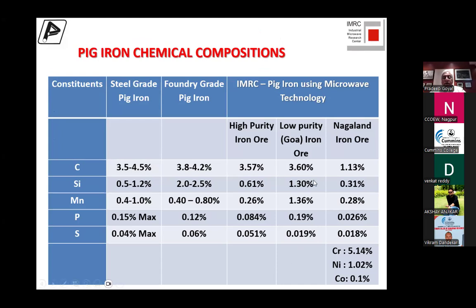And here you'll see that then we took the low purity Goa iron ore, and this is the chemical composition of that. We tried another experiment with Nagaland iron ore, which is magnetite iron ore, which nobody uses in the world. We decided that we will try to melt that also and reduce that in our microwave. And we were really shocked and surprised that we were able to process it to very low carbon. You can clearly see that this is almost akin to a steel chemistry, just a little bit of removal of carbon. And then we also recovered chromium, nickel, and cobalt, which were there in this magnetite ore, which was a surprise find.